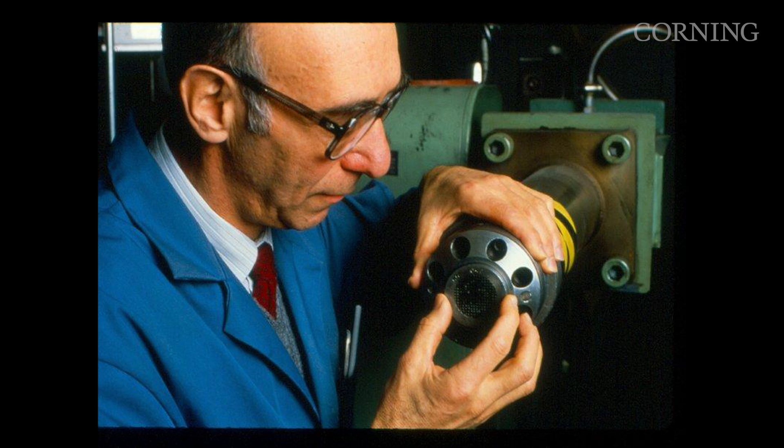We had neither a material nor a process at that time. We did have experience making ceramic radomes, which could withstand great thermal shock and high temperatures, so it seemed ideal. Cordierite has the extra advantage that it can be batched as a mixture of clay and talc — very inexpensive materials. There was some pressure, particularly because we didn't have a process.